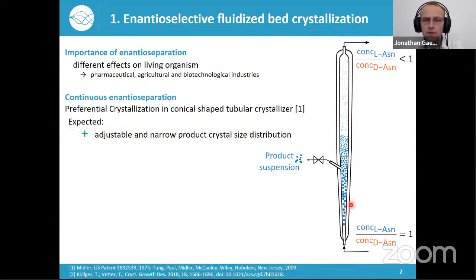First, we have this conical shape, and due to this conical shape, we have a varying fluid velocity over the crystallizer height. And this results in a size classifying effect. That means that our larger particles will be located here at the bottom of the crystallizer, and smaller particles will be located here at the top of the crystallizer. So we can expect that our product, which we can withdraw here as a suspension, has a narrow product crystal size distribution, and that this distribution is also adjustable via the volumetric flow rate.